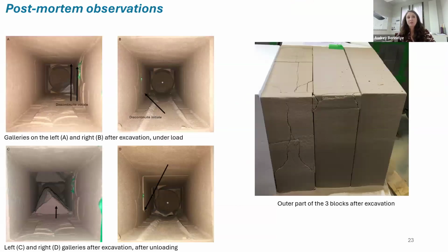We can also do some post-mortem observation. So from the intact slice toward the one that looked like a puzzle from the previous slides. And we see, for instance, here is how the excavation looks. You can see that it's truly a squared tunnel that we're drilling, with a rounded shape at the very end of the block. And we see that in the case of our experiment, we just see some blocks that are falling after the unloading of the whole experiment.